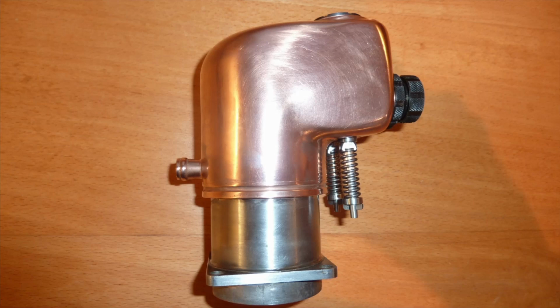There'd be no significant pressure caused by the coolant in use, as the system would be open to atmosphere, but there would be stress set up by unequal expansion because you've got copper bonded to steel, and vibration, of course, when the engine was running. So I pressure tested each one with air up to about 10 psi, and they were all okay.